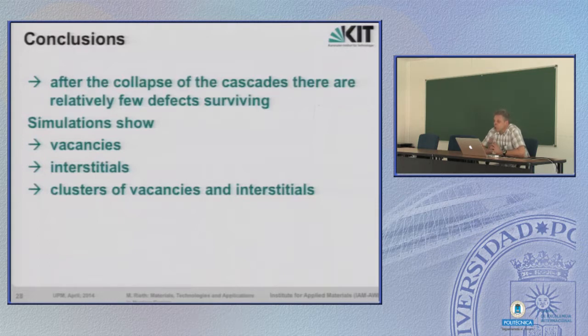So after the collapse of a cascade, there are relatively few defects surviving. That's important. Otherwise, materials would probably completely dissolve under irradiations. And the simulations show that we have to deal with vacancies, with interstitials, and with clusters of vacancies and interstitials. These are the main defects produced by irradiation and by these cascades.